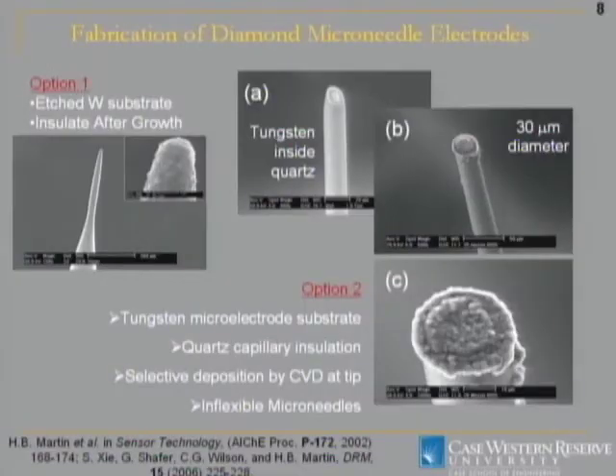So our initial electrodes were based off of trying to mimic the carbon fiber microelectrodes used in neurochemical sensing. These are capillary-based electrodes where you pull the capillary to a fine tip. In this case, they would start out with a fiber inside the capillary, and they'd pull it and form a disc electrode.